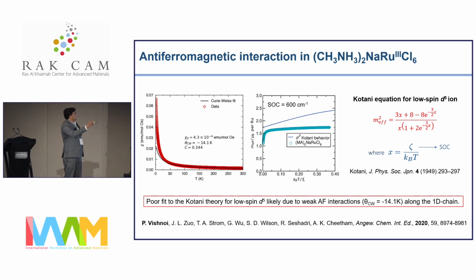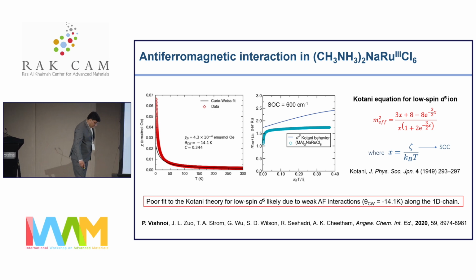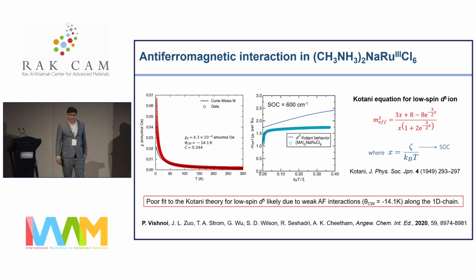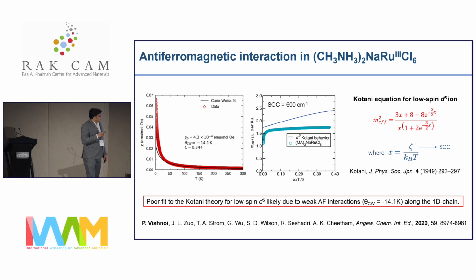And this is the sodium-based system where we see the Curie-Weiss theta is about minus 14 K. This is a weakly antiferromagnetic system, as is likely along this chain. And then we analyze this data.